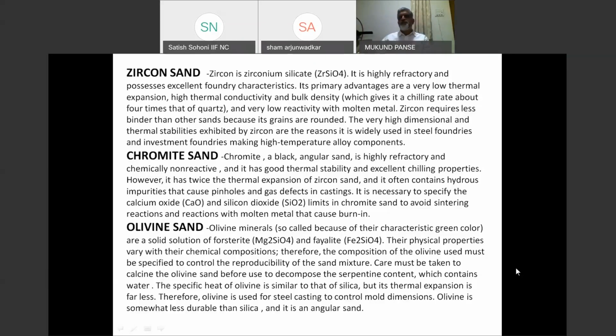However, with zircon sand full molds, it is difficult to make castings, as the metal gets chilled and you get a lot of cold shuts. Zircon sand is being used only for chilling purposes, so that sand doesn't fuse in heavy sections of a steel casting. Advantage of zircon sand is you can mix it with silica sand, 50% zircon, 50% silica, something like that, to get the effect of both the sands. You can reduce the consumption and you can have some effect of neutral chemical reaction. But again, this use is restricted to heavier junctions only.